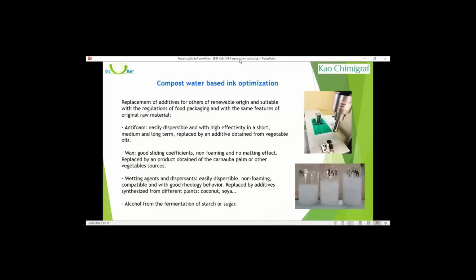The optimization that we have carried out consisted of replacing those additives for which we found a renewable alternative. First, we contacted our regular suppliers and other new ones looking for products of renewable origin. Next, we verified their compatibility with the standard matrix, and finally, we evaluated their effectiveness and the interactions with other properties of the ink. For instance, with the defoamers, we checked their dispersibility, because if the defoamer is not easy to incorporate, it will probably produce printing defects.